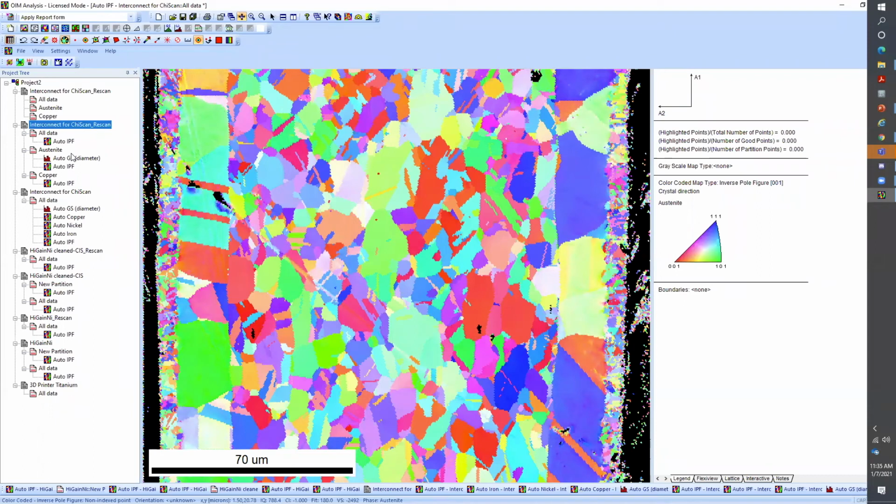How many of those are background? Then if I have a multi-element sample, how many of those are going to be other elements? Suddenly your 1,000 counts per spectrum is like 5 or 6 counts on peak for the EDS signal. So you really have to be cognizant of how many counts you're actually getting through that are included in the actual EDS signal itself.